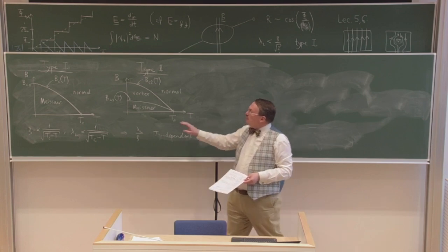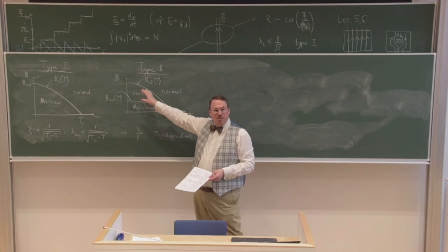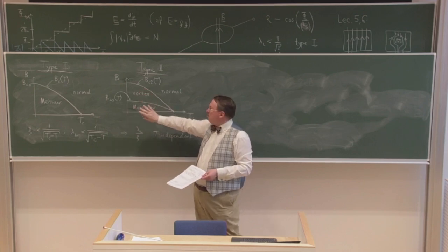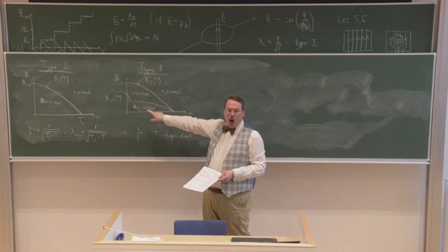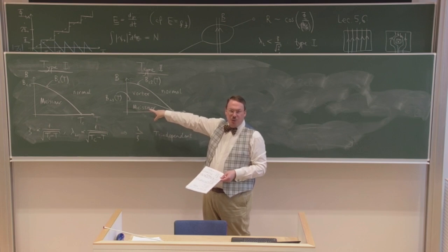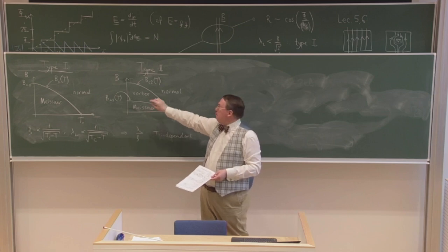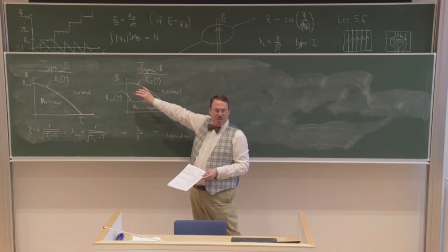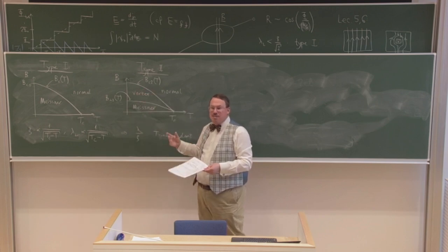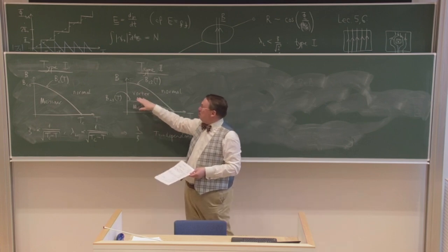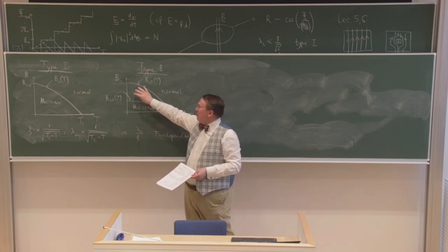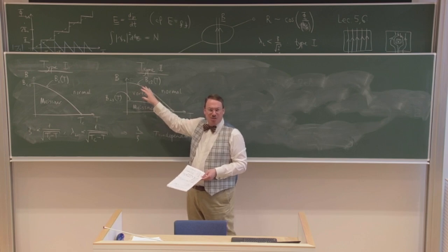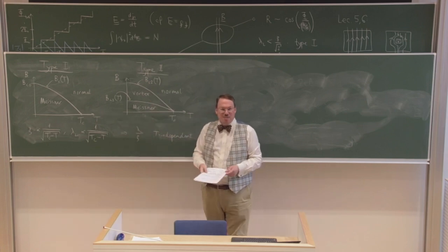And as we've discussed, disorder effects can be important in the vortex phase. So actually in this ideal phase diagram, only the Meissner phase would show a transport signature of superconductivity. There would be resistance because of vortex motion in the vortex phase. But if you have some disorder, the vortices will pin, then you may find that this vortex phase splits into a sort of vortex solid and a vortex liquid, and there's all sorts of interesting stuff there.